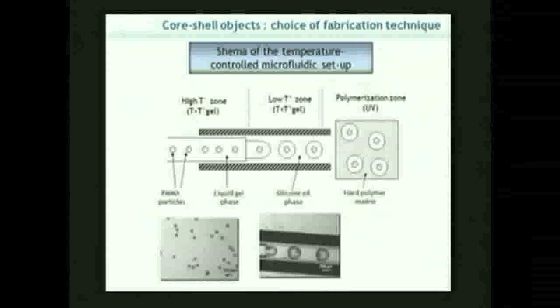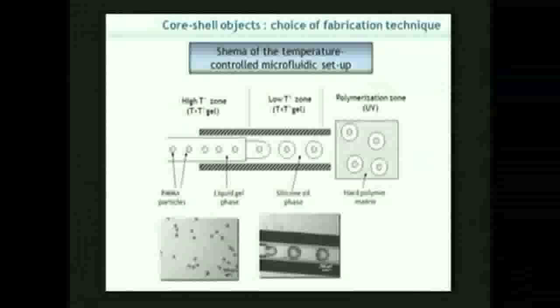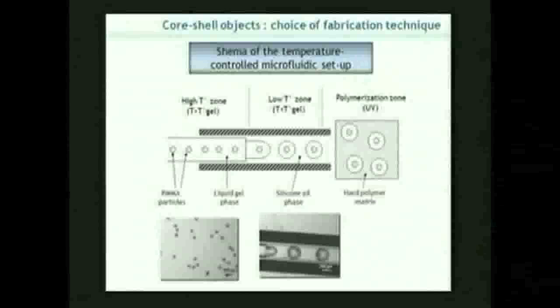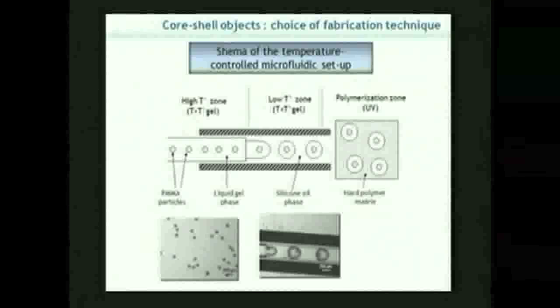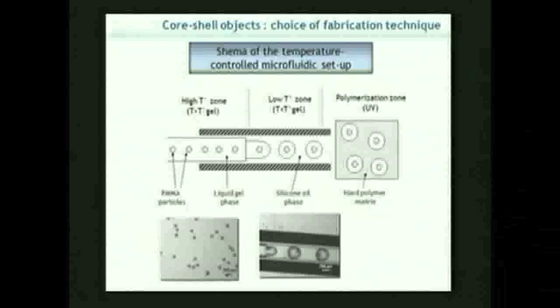You have the flow of PMMA particles contained in the gel at high temperature, okay, and you push that into the capillary tube, and here in the other capillary you have a co-flow, okay, so you have another flow here of another phase, and in that case this is a silicone oil, okay. So you have here some PMMA particles in the liquid gel phase, which is pushed into the phase which is made of silicone oil. The phase of silicone oil is called the carrying phase, okay, and the phase containing the droplet is the one that will be encapsulated like this, okay.